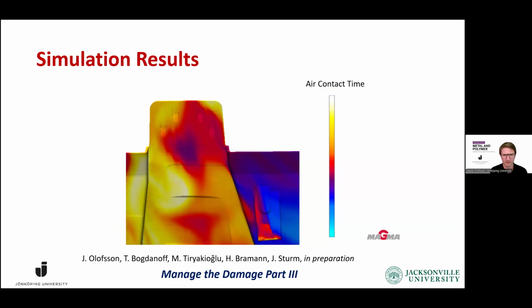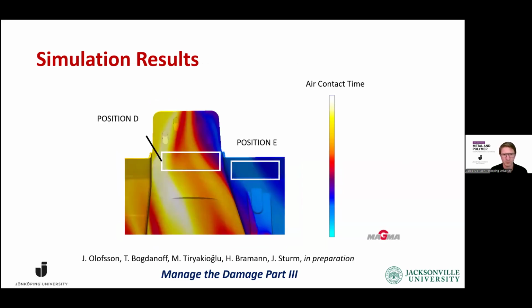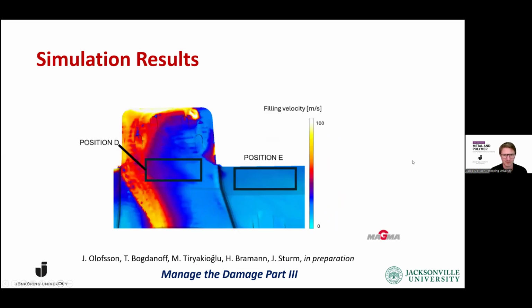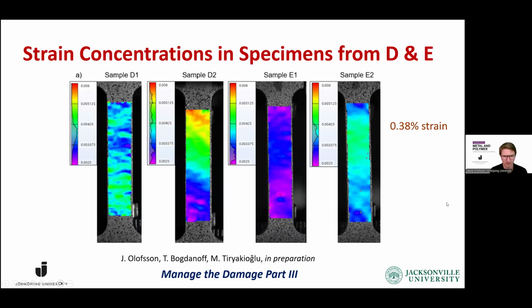And as the filling continues, in the next slide, which is the last one, we see that this position D has been subjected to a significantly higher air contact time. So the time during which the melt has been mixed with air, and the possibility to create more oxides, is much higher in position D compared to position E, which is just next to it. Geometrically, they are very close. Also looking at the velocity that these positions have been subjected to, we see that position D has been subjected to higher velocity during the filling. So there's been a much more turbulent flow of the melt that comes up here. So that could be a possible explanation for why D is different.